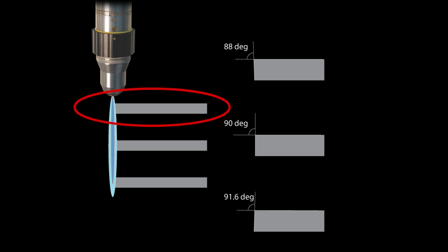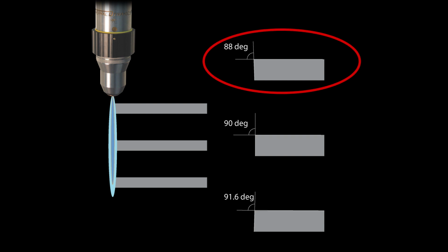If the distance to the plate is small, the closest part of the arc in relation to the torch is doing the cutting. This creates negative bevel, meaning the top surface is bigger than the bottom surface. Too small a cutting height is also prone to collisions.